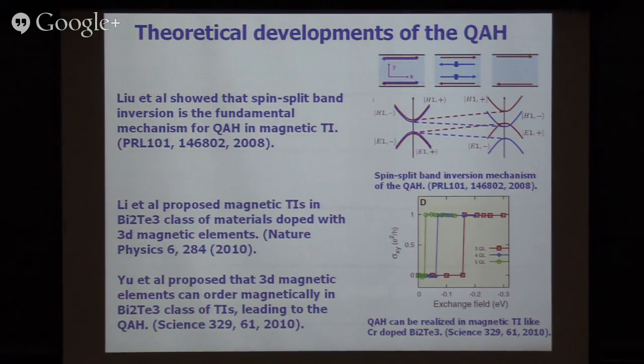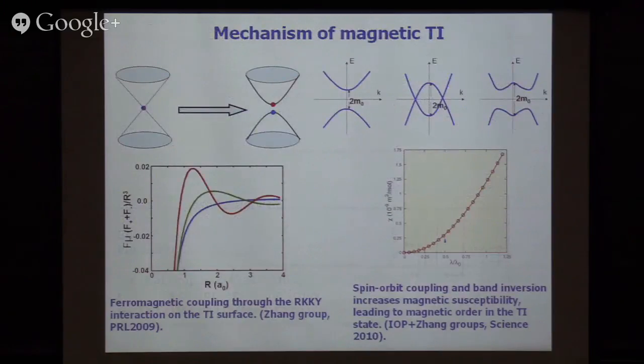And the first surprise is that these will form a ferromagnetic insulator, which is already very, very rare in nature. But we further predicted that this ferromagnetic insulator would have an exactly quantized Hall conductance or Hall resistance. And the mechanism for this ferromagnetic insulator can be basically explained by two somewhat complementary pictures. So remember that you have a surface state which forms a Dirac cone. In condensed matter physics, there's a well-known idea that if I put magnetic moments into a conducting material which has a Fermi surface, it mediates a magnetic interaction which oscillates at a periodicity of 2k_F.